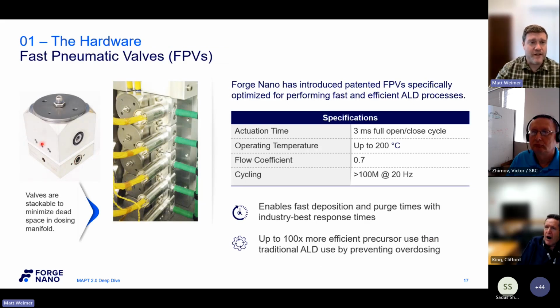So here's what our fast pneumatic valves look like. If you notice, they don't have those VCR stubs on either side, and that's very intentional. Those VCR stubs are extra dead space that need to be purged with each half cycle. Quite simply, the more precursor you put into a chamber, the longer you have to purge. That's always the slowest step in the ALD cycle. So the more you can minimize that dead space, reduce that amount of precursor in the chamber, the faster your purge time is going to be, plain and simple.